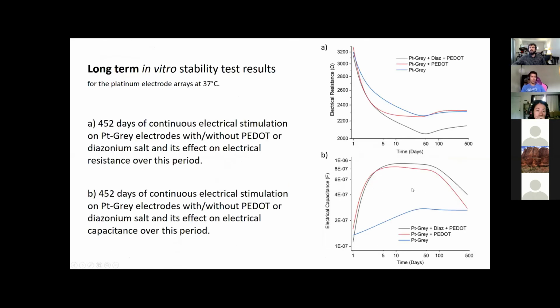And then in the case of platinum gray, first we had just platinum gray over time. And then we had the PEDOT. You can see electrical resistance drops. Day 2 is when I plate the coating. And then you go on, it retains its improvement. And if you have platinum gray, diazonium salt and PEDOT, it drops, but over time, it really helps to keep the low resistance.